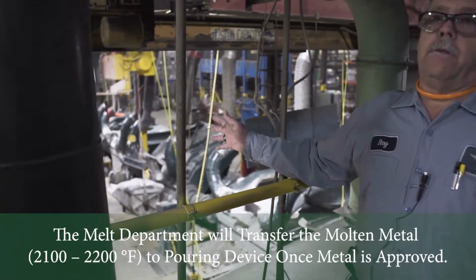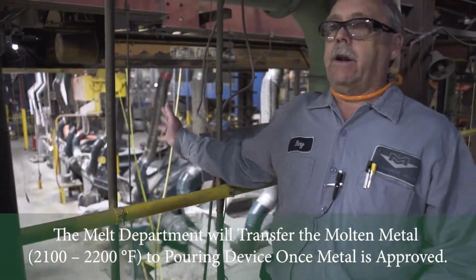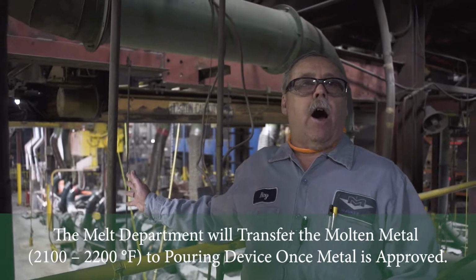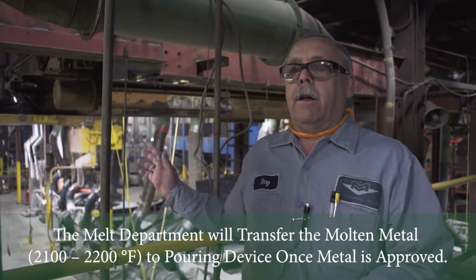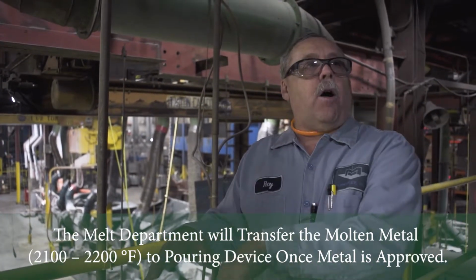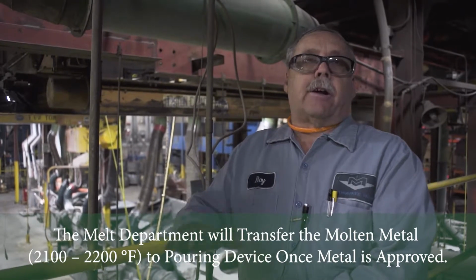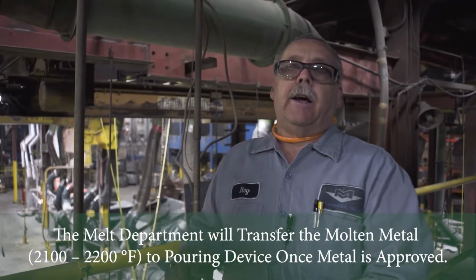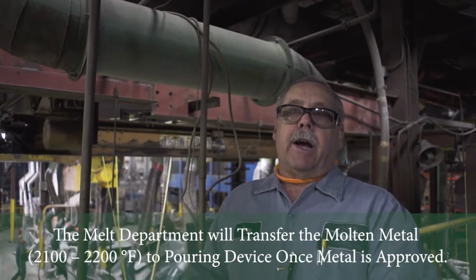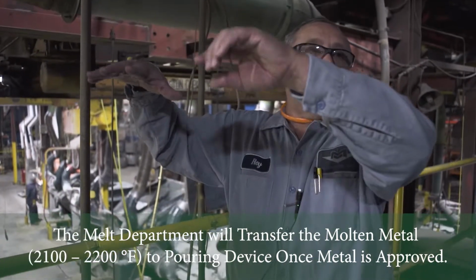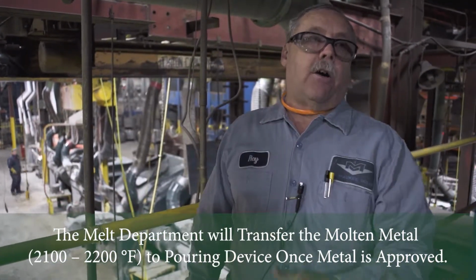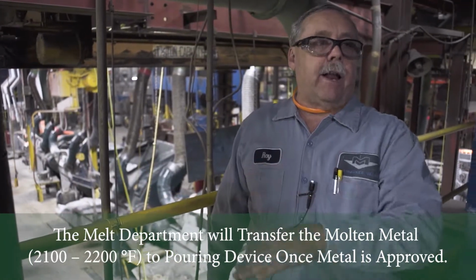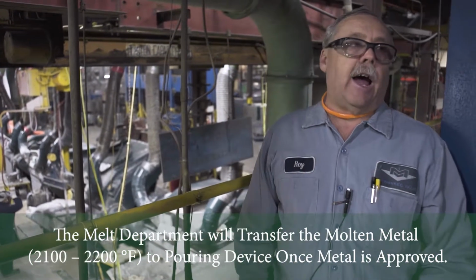As he's monitoring, we bring the metal over, and we don't shut down to fill the auto pour with metal. So when the metal is poured back into the auto pour, he has to close down that orifice opening a little bit at a time because we have hydrostatic pressure increasing. Then he has to open it up as the metal goes down to match that time each time.